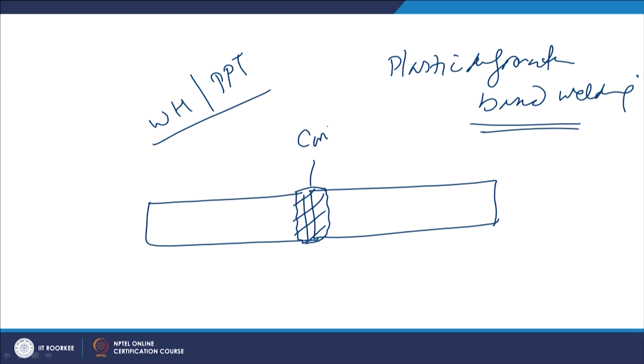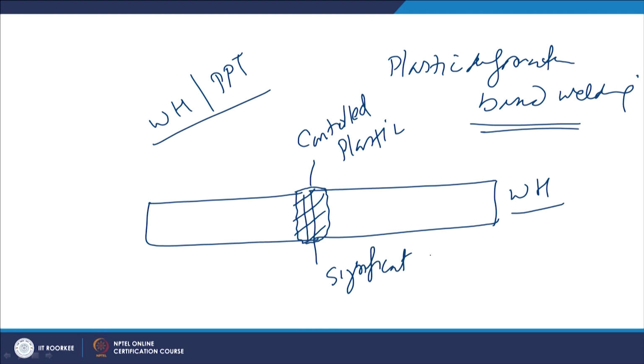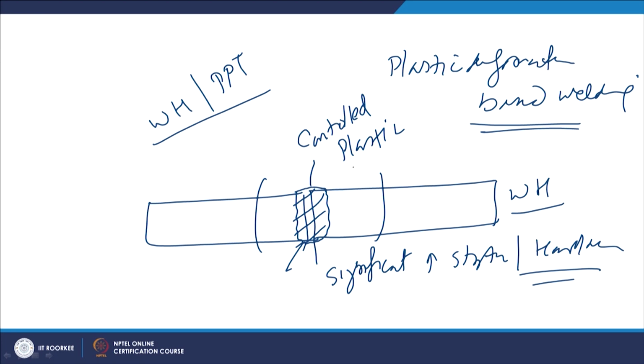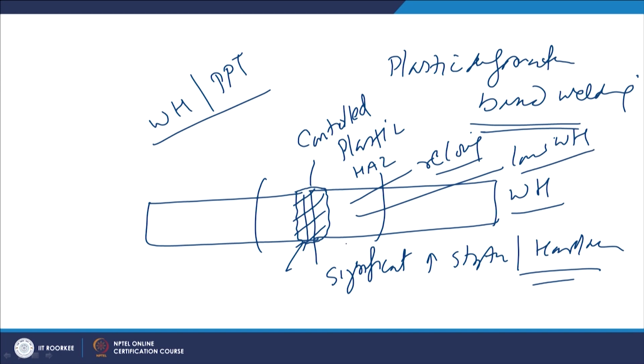This controlled plastic deformation in case of the work hardenable metal systems causes work hardening, and so a significant increase in strength as well as hardness takes place in the region of the weld joint. While away from the weld joint in the heat affected zone, if heat is generated due to the plastic deformation in the course of the welding process, then this will lead to the recovery and loss of work hardening effect, and this loss causes the reduction in hardness and in yield strength.